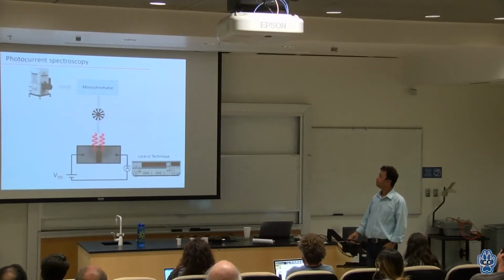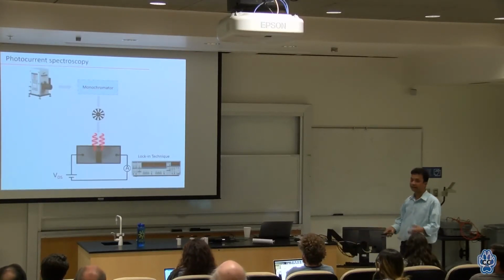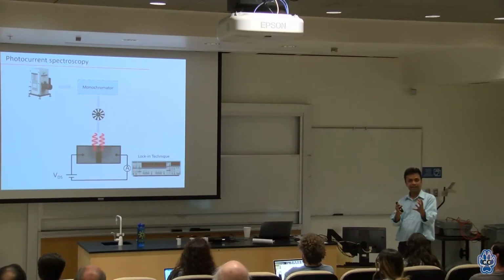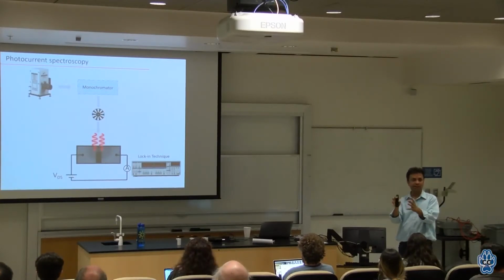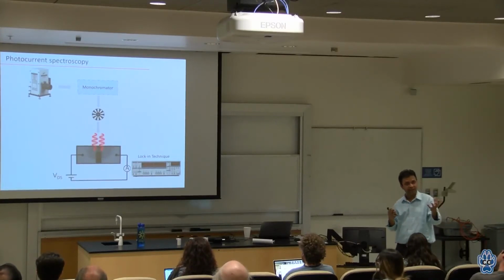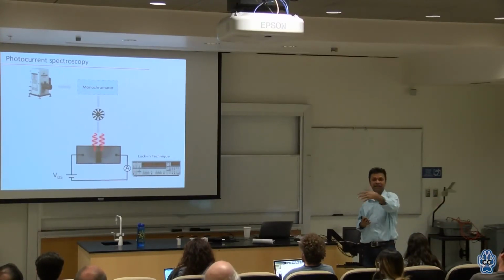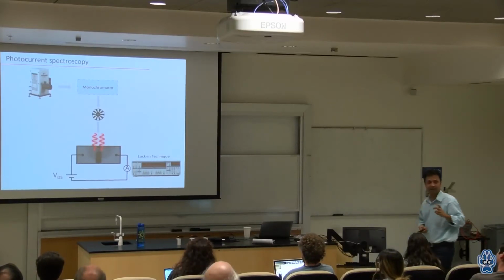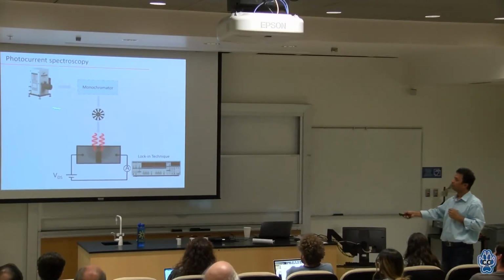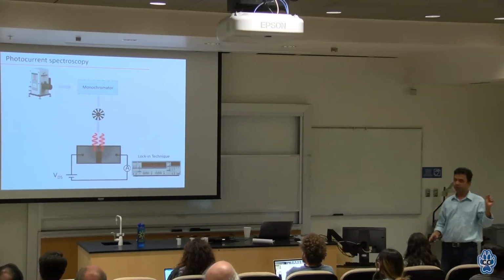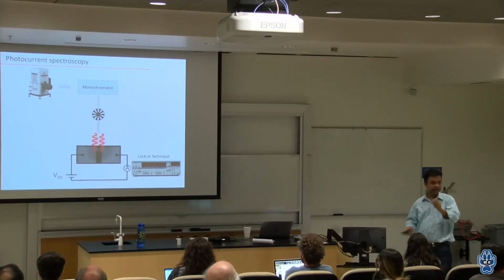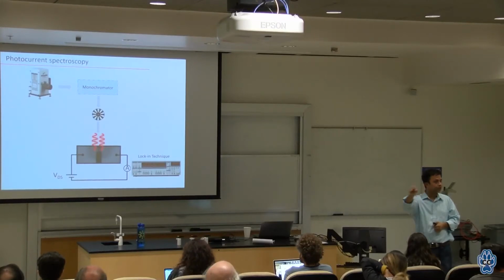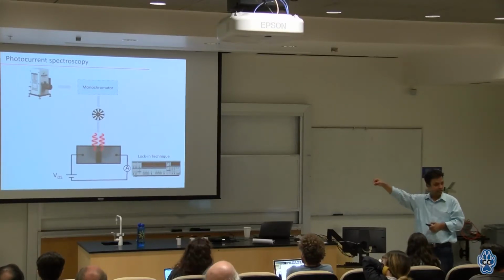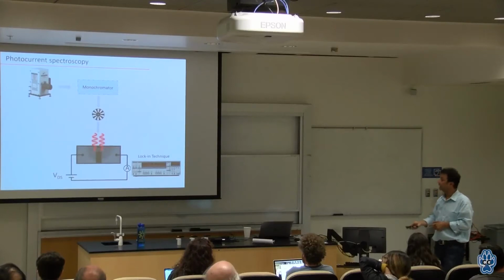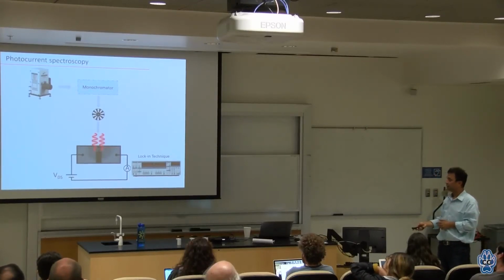Very quickly, one of the studies we do in the lab is photocurrent. It means you hit it with different colors of photons and see what kind of current comes out. From there you can tell the electronic band structure and the quasi-particle behavior of these materials. We have a monochromator that can selectively select the photon color from red all the way to green or UV. And then we measure the properties.